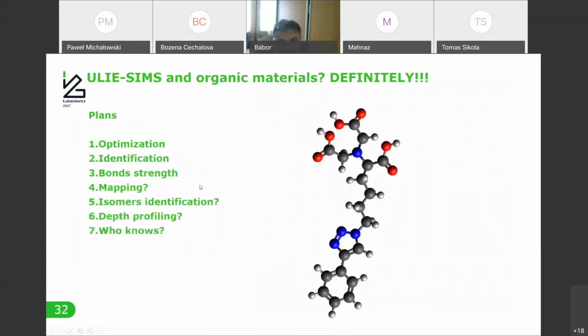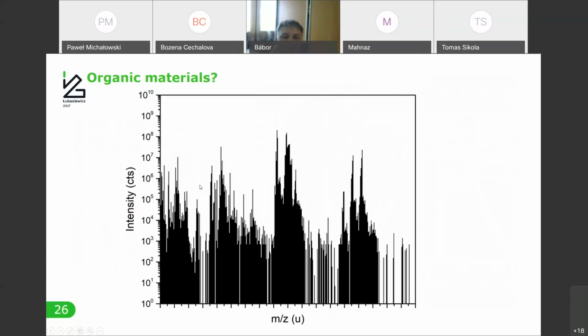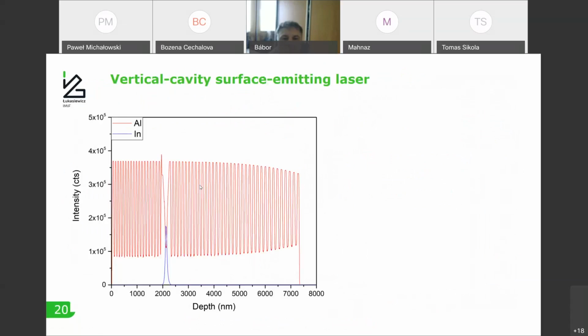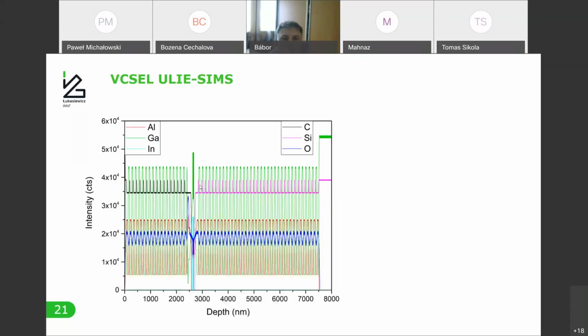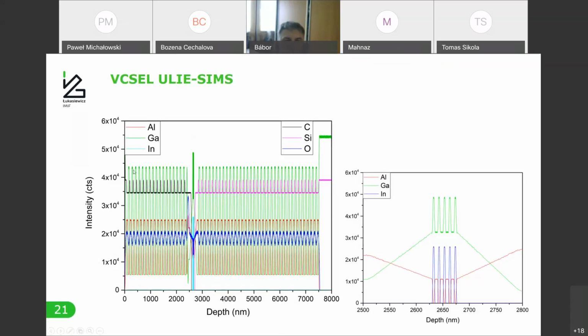So that's for graphene. And in here, that was the problem, that actually I wanted to show more examples without going into too many details. But in this case, there are a lot of things happening here. So what I basically did was that the sputtering was with, I think, 250 eV for most of the DBRs. But when I reached the region close to the quantum wells, I used 100 eV to obtain very good depth resolution. So I also changed the impact energy in between.